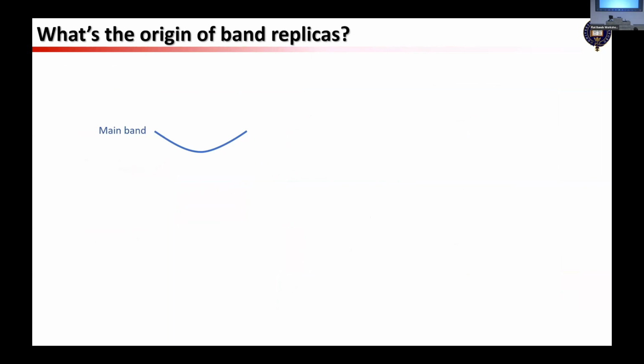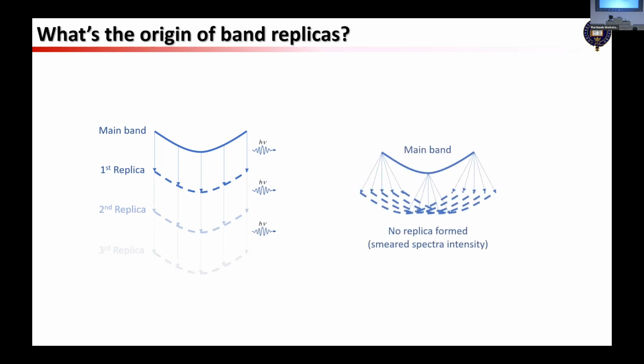If we have the main band, what we saw is a first replica, where the energy gets dissipated by something, which could be some sort of boson. And if this interaction is strong enough, then you have a second replica or even higher order replicas. At the beginning we saw the replica right underneath the original flat band. We thought this boson should reside around the gamma point, because there's no momentum transfer.